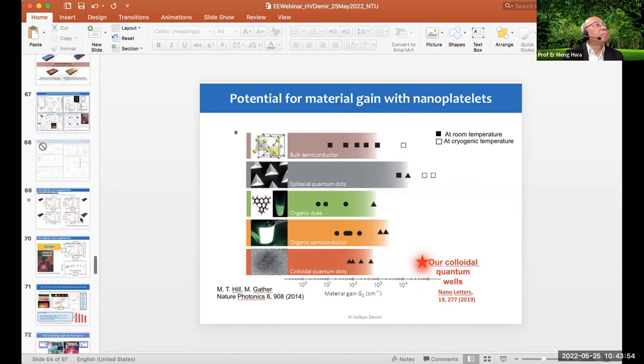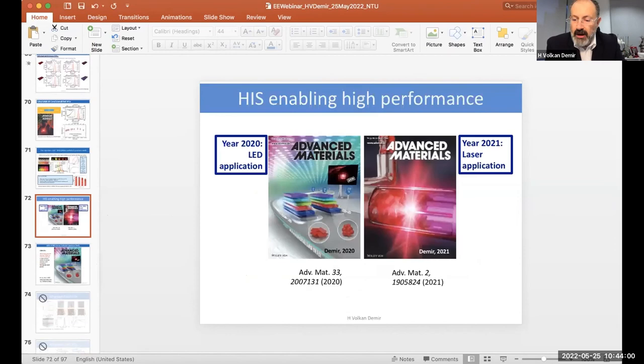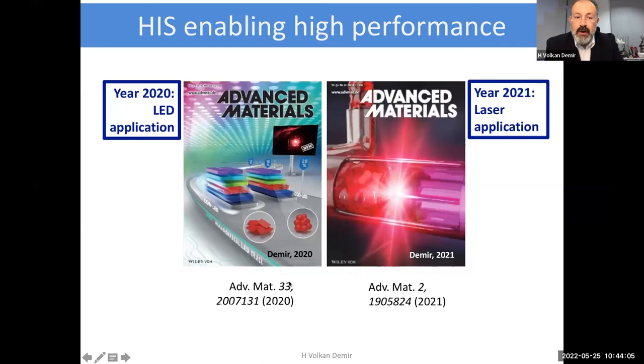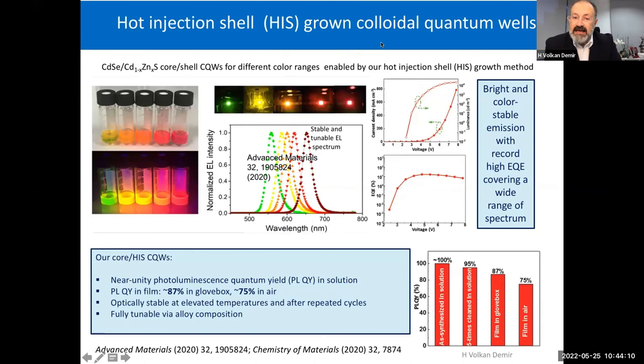So this puts us now into quite recent work, where I can show you using this type of nanoplatelets, as we nickname them, in the form of atomically flat nanocrystals, also known as colloidal quantum wells, and developing new multi-layered architectures. For example, using hot injection shell, we can achieve quite high efficiency, near unity efficiency as synthesized. And these are quite robust material systems. Indeed, very, very harshly washed, they still survive with high efficiency. And without using any additional protection, we can actually maintain high efficiency as well.